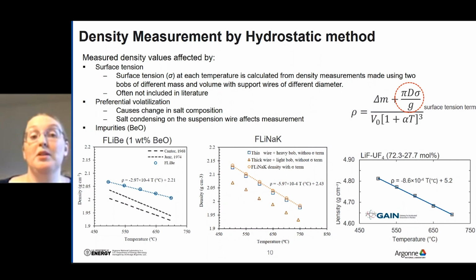So we have determined over our many years doing this now, the surface tension, while frequently neglected in literature, is actually quite important to the value you measure. The surface tension is not insignificant, as some like to claim.